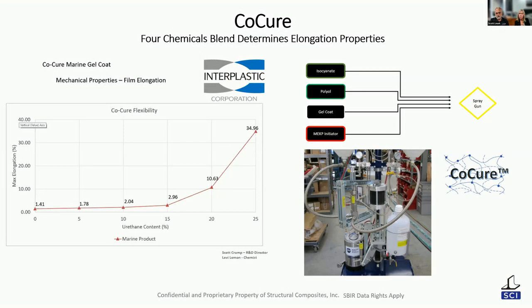And we can change the urethane constituents. And as we change that, we change our properties. So at first, we were really just focused on elongation. Polyester is great. It's low cost, but it's brittle. If we can get the brittle nature of it gone, we're counting on the fibers for strength. We could have a resin that could perform very well.